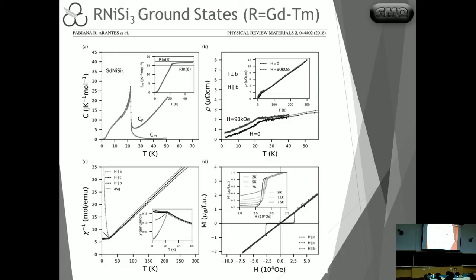For example, for some reason that we still don't know why, you cannot saturate the magnetization of these crystals in any direction of gadolinium. There's actually a metamagnetic transition here, down here, but after that you can see that we are still far away from the saturation moment of gadolinium here, even up to 6 or 7 Tesla, which was the limit that we had in this case.